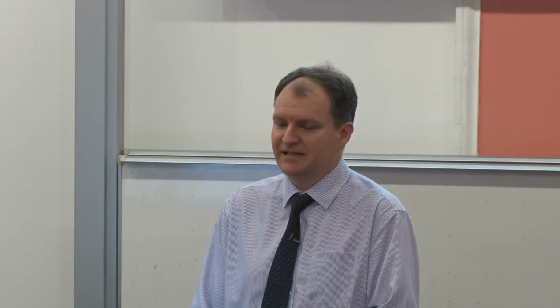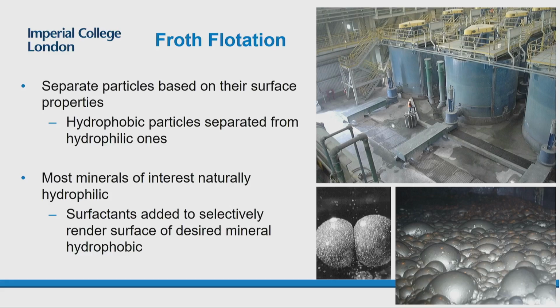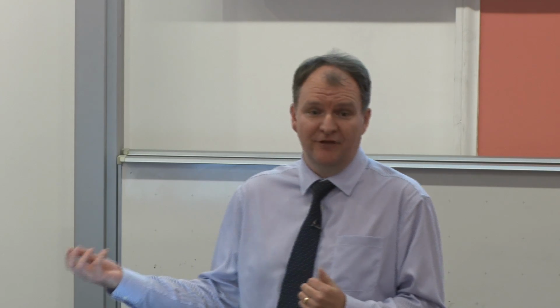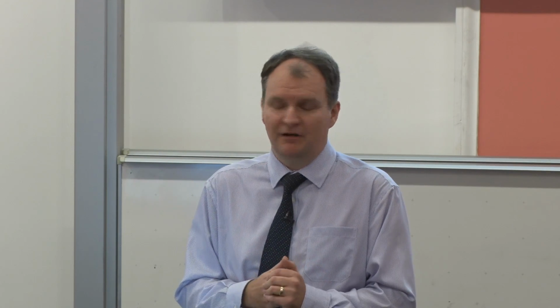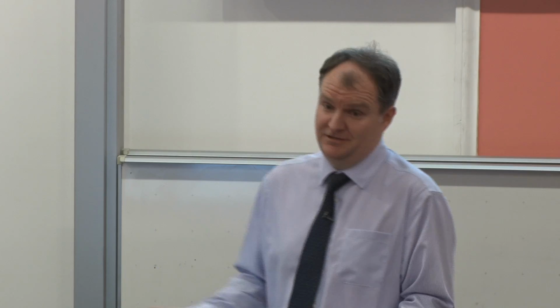So you need to get your material from these days' 0.5% that is coming in, up to maybe 20 or even 30% to feed it into the smelters. And froth flotation can do this for you. Froth flotation is a way of separating minerals you want from the minerals you don't want, and it does so based on hydrophobicity. So you basically do it based on how water wetting the particles are. If you have some particles that are hydrophilic, so want to stay within a water phase, and other particles that are hydrophobic, so don't like to be water wet, if you bubble air through a mixture of those, the particles that are hydrophobic will stick to the air bubbles, and the particles that are hydrophilic won't stick to the air bubbles, and so you can carry the particles you want to the surface of the froth and therefore recover them.